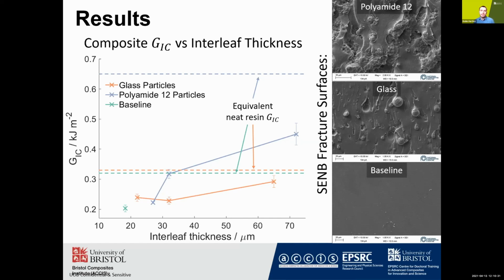Now, the important thing to consider here is that when cracks propagate through interlaminar regions, they're not utilizing the full fracture toughness of the resin. This is especially true when you consider that a commercial interleaf system will have interleaf thicknesses between 20 and 30 microns. So you're not going to be getting up to these very thick interleaves where you get enhanced fracture toughnesses.